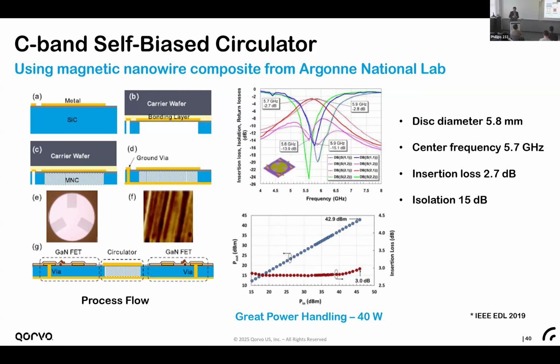And because it's lower frequency, the disc size is relatively big. It's 5.8 millimeter. It works well in the C-band, although the insertion loss is still a little bit high, 2.7 dB. The material still requires some further maturation. We are looking at that right now. But the great thing is it can handle 40 watts. This is very, very high power. Think about how much heat it would generate if you have 40 watts from your device. Especially for defense applications, it offers great opportunity in the near future if we can incorporate it into our radar system.